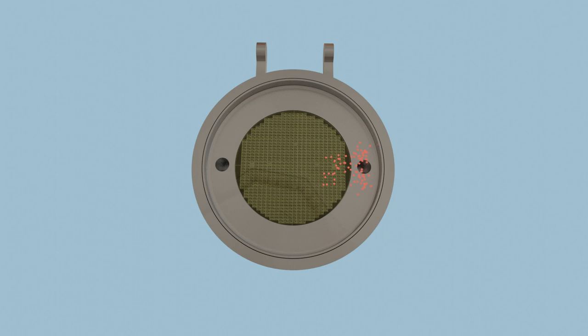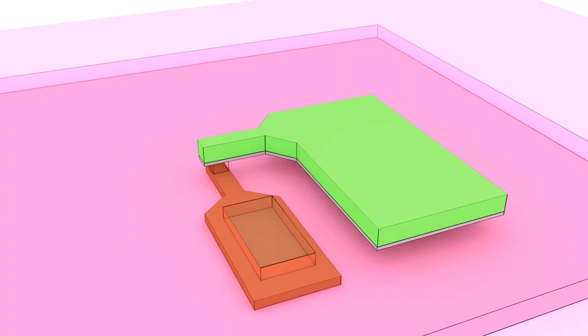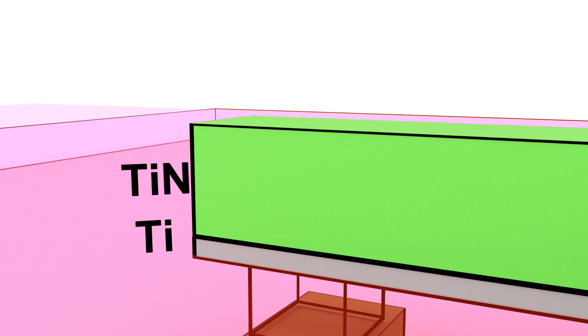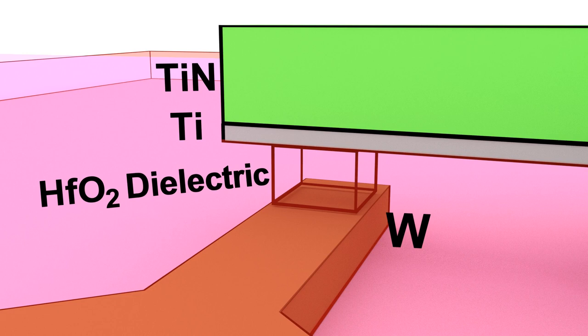The top electrode, consisting of a 200 nanometer titanium nitride on a 10 nanometer titanium layer as oxygen getter material, was deposited by magnetron sputtering and patterned by photolithography and liftoff.